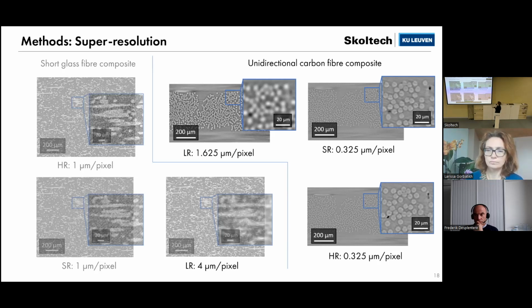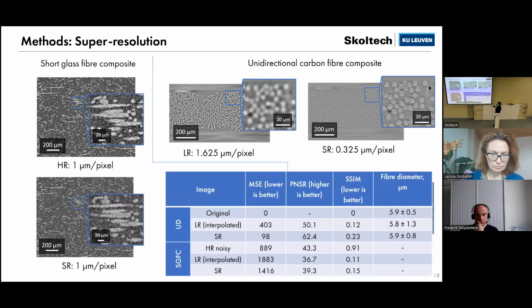for quality enhancement. And if we look at the metrics, we can see that all the metrics were improved, image related metrics here, and also fiber diameter as a physical related metric for unidirectional fibers.